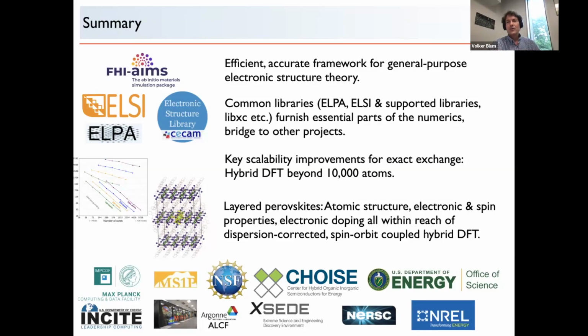And you see that if you go to different materials and look at the impact of the material, the spread of values that you get out from DFT is about 0.8 electron volts wide, as you can expect. So HSE will have trouble getting you much better, and then it becomes very chemical element dependent. And so we wanted something that at least would not introduce arbitrariness into our calculations by having to guess the experimentally relevant value before we knew it.